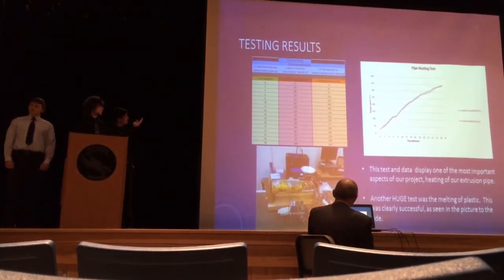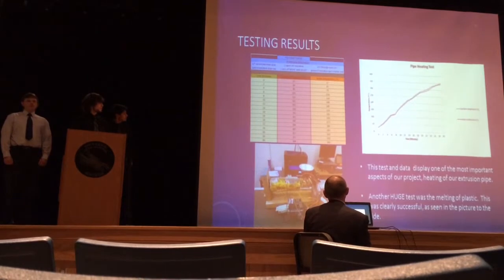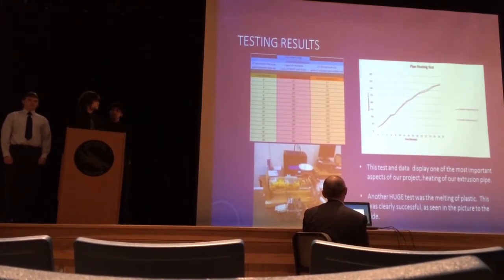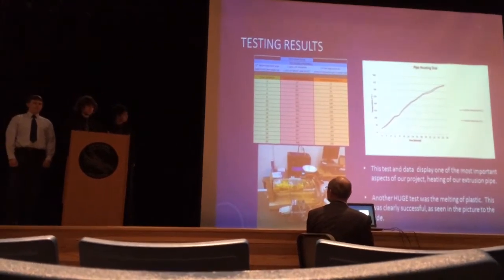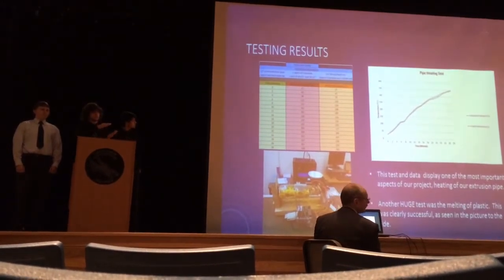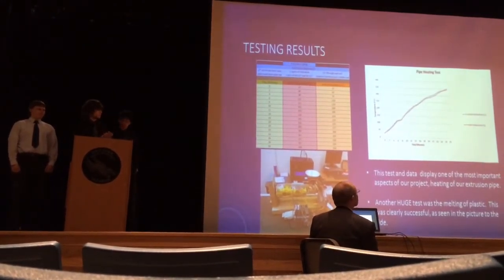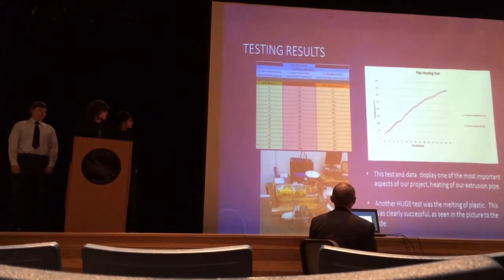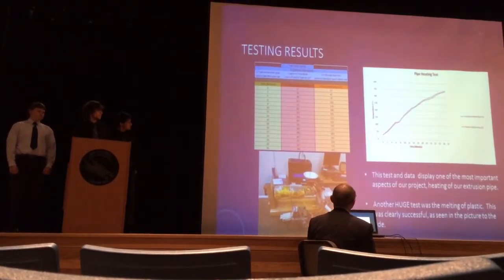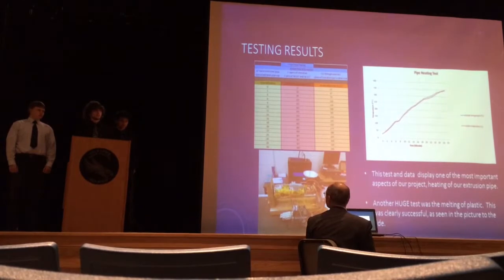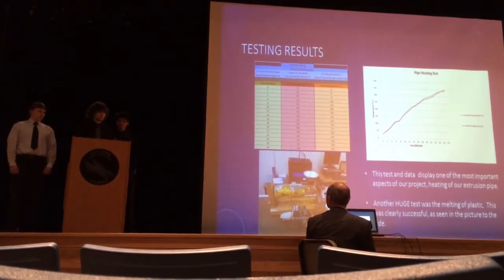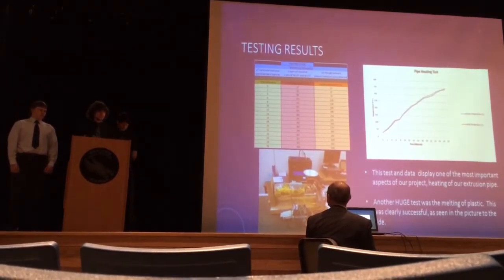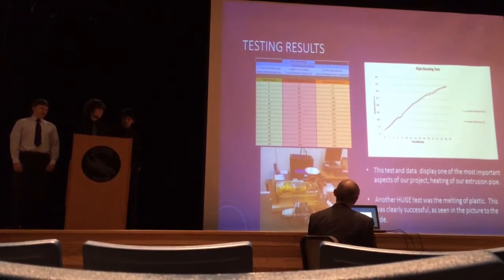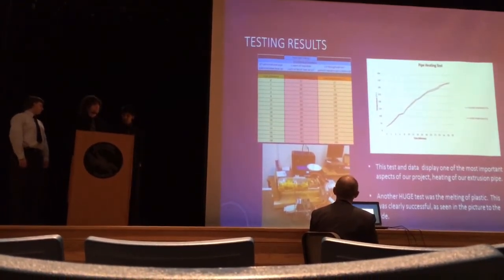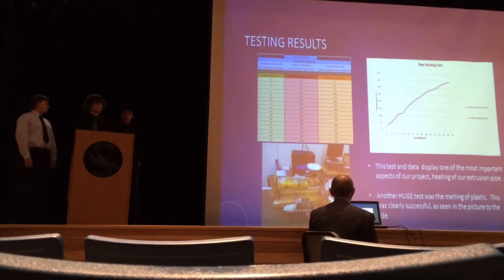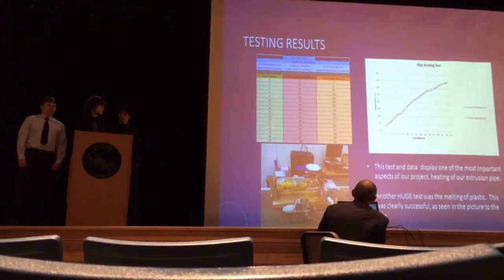So what we did is we came up with this test here, and over a 30-minute period, every 2 minutes, we took the temperature of both the inside and the outside of our extrusion tube, and then we plotted it on a graph. And as you can see, there is very, very little difference. So ultimately, we decided to place our temperature probe on the outside of the pipe and adjust slightly for the temperature difference that there was, and we rolled with that.